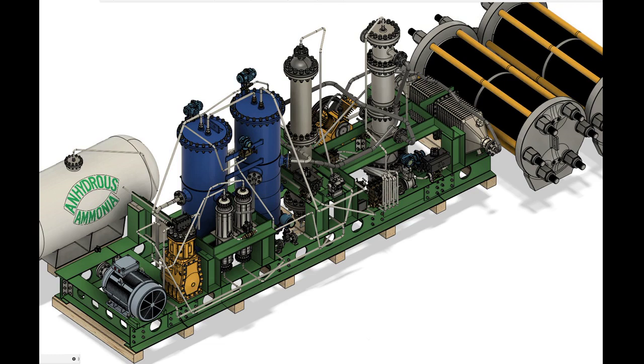Inconel 625 has a yield strength of 472 megapascals at 500 degrees Celsius. A reactor vessel with an inside diameter of 104 millimeters, and an outside diameter of 134 mm, will experience 171 megapascals of von Mises stress at an operating pressure of 33 megapascals, rendering a safety factor of 2.76. Inconel 625's yield strength only declines 20% from room temperature to 500 degrees Celsius.